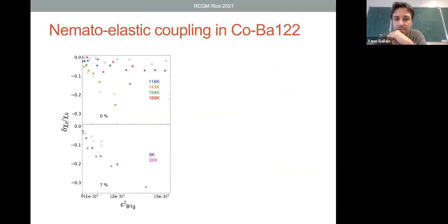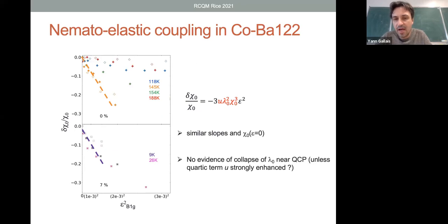And in fact, plotting them as a function of epsilon square, which is the expected behavior, you have a slope that is very similar between both compositions. So since chi naught is essentially very similar from Raman measurements under no uniaxial strain in these two kinds of composition, that sort of indicates that a collapse of this lambda square is unlikely unless there is a huge enhancement of the quartic term. So from the point of view of these elasto-Raman measurements, the nematoelastic coupling does not seem to change so much.